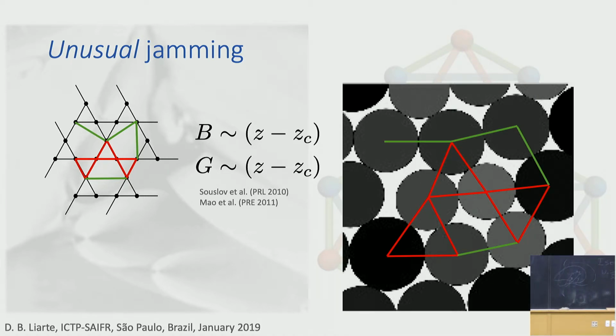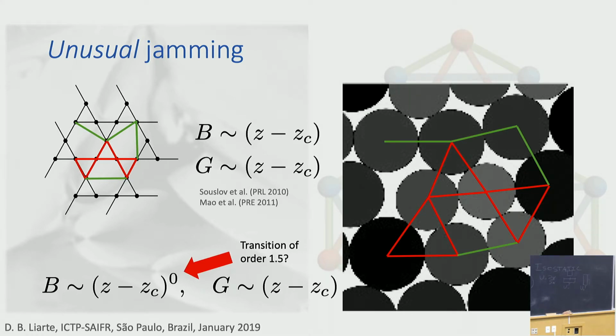And it has a transition where the bulk and shear modulus go to 0 at the rigid percolation transition. Now, rigid percolation is different from jamming in an important way, and that's what I'm trying to emphasize here. In jamming, you have this kind of unusual behavior where you have something that looks like a first-order phase transition and something that's like a second-order phase transition. Whereas in the general rigid percolation case, you have something that has mixed properties of first and second-order phase transitions. So to have a model starting from a random elastic network that gives rise to the right properties of jamming, you have to start with other kinds of lattices.